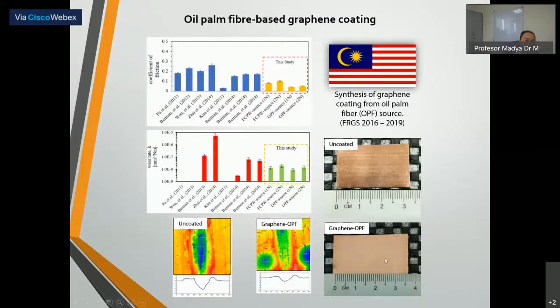This is the OPF graphene, coated graphene, and then this is the uncoated, the naked copper. And then when we compare our graphene with other studies that grow the graphene using commercial feedstocks like the hydrocarbon, we can see that our coefficient of friction, our graphene is most likely lower than others, and also the wear rate.